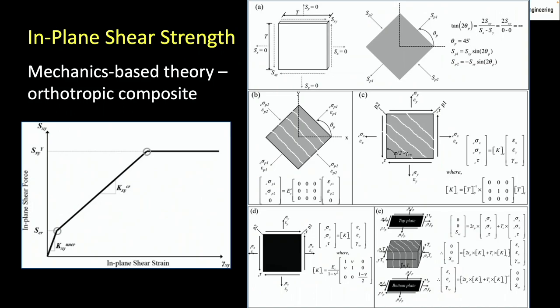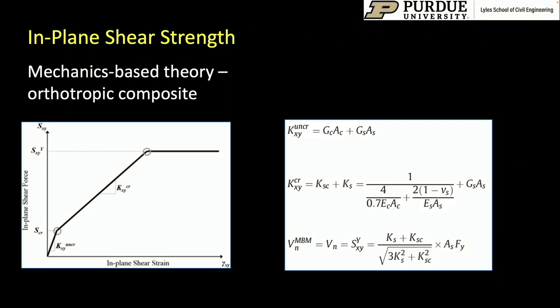And what it comes down to is that the behavior is governed by mechanics, the orthotropic composite mechanics of this system. When you have this system subjected to pure in-plane shear, the tension component of that in-plane shear causes cracking in the concrete. And the compression is resisted by that cracked concrete. Together, you get an orthotropic system with zero stiffness contribution from the concrete in the tension crack direction and with almost complete stiffness in the compression axis. We were able to put all of this together into a simple mechanics-based model that resulted in an in-plane shear trilinear curve that explains the in-plane shear behavior of the system, which provided equations for that stiffness for the composite section before cracking, stiffness after cracking, and the in-plane shear strength, which corresponds to the limit state of von Mises yielding in the steel plates, resulting in this equation for calculating the in-plane shear strength.